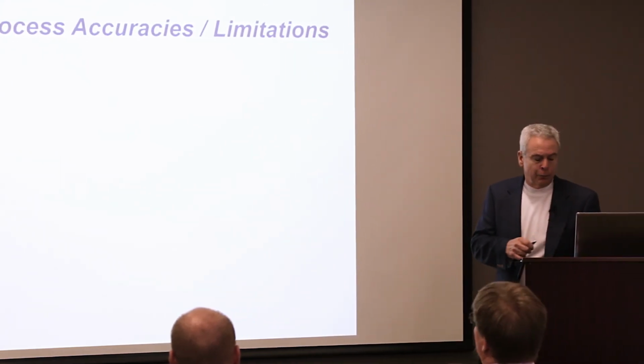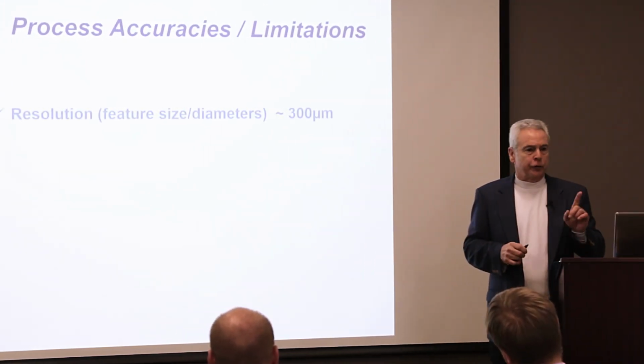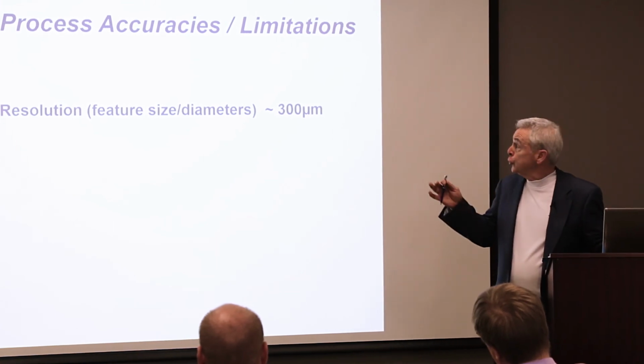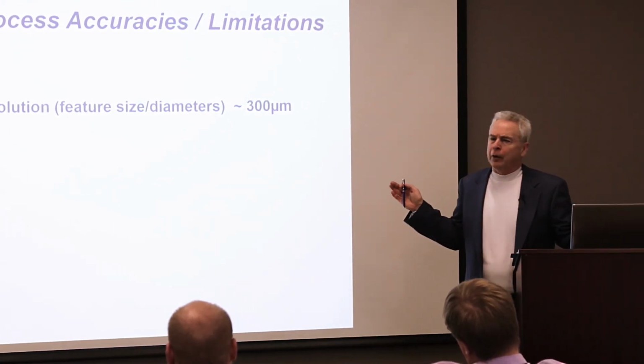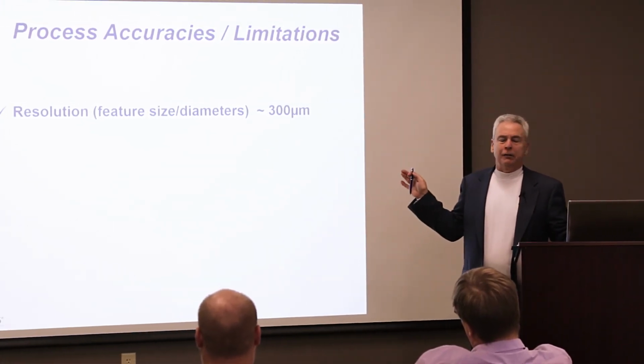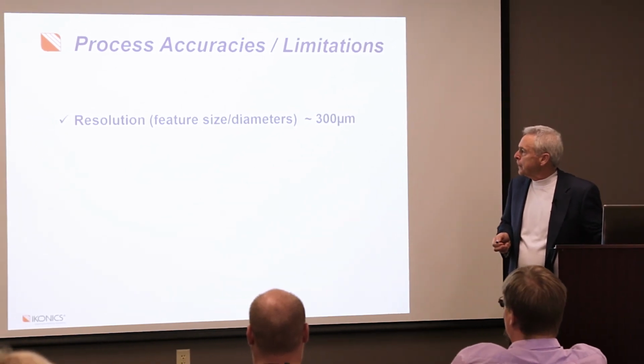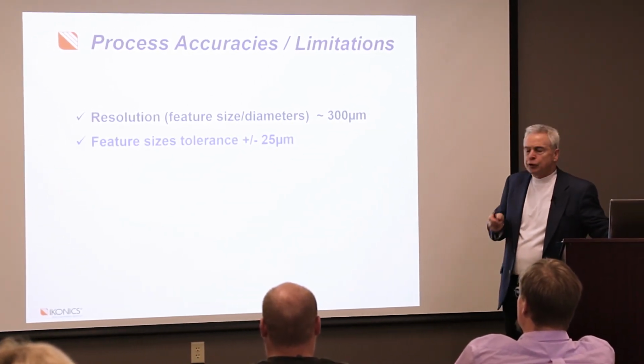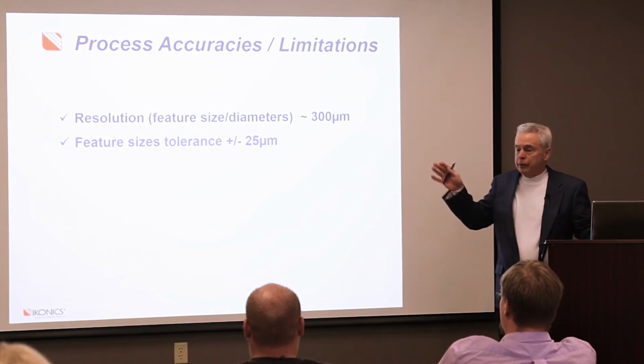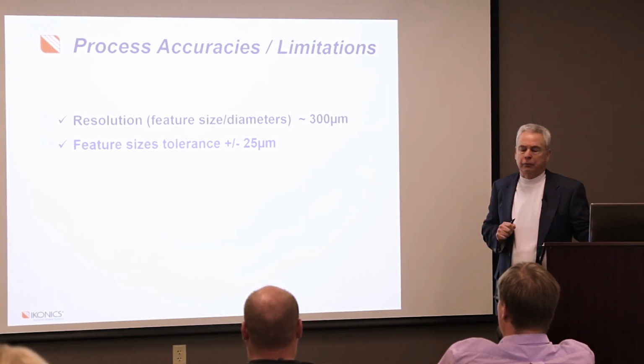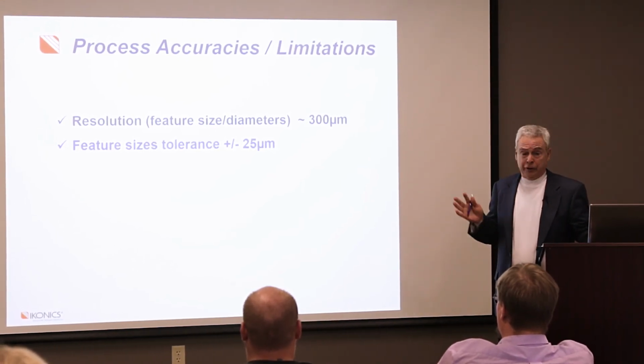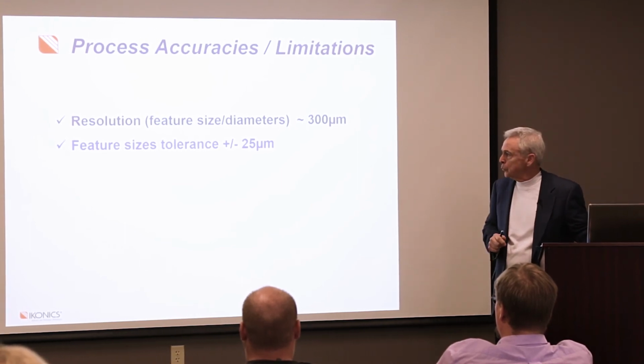Now, the process does have some limitations. Let's talk about those just real quick. Resolution, you're limited to about 300 microns. For this industry, that's pretty good and not a problem. Feature size and tolerance, you can locate these features within 25 microns of each other. Again, for this industry, more than enough.